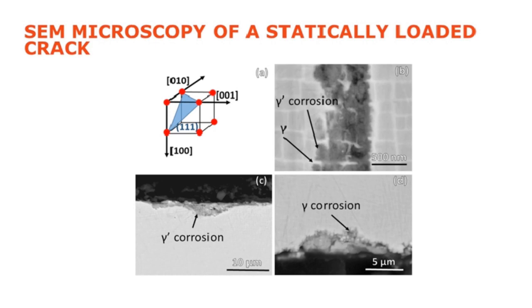So what we can see again, and it echoes what I was talking about earlier, we can see the crack propagating on cube planes, so 100, 001 and 010, and we can see corrosion interacting or preferentially attacking the gamma prime. And image C there is showing what looks to be an early corrosion pit with again corrosion interacting preferentially with the gamma prime. Image D is actually showing slightly the opposite.